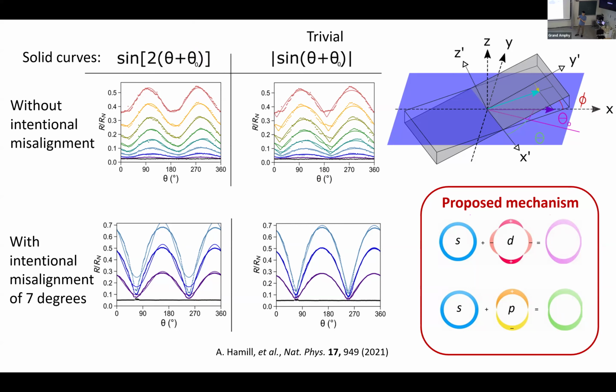However, I think maybe there are some tuning parameters that we may not really account for. Maybe this trivial effect is not just that trivial. We need to have something else. However, if we are really serious about this twofold symmetry, then they propose that the pairing order parameter is not just pure S wave, because S wave is isotropic. Then you need something to give this twofold symmetry. So either it's S plus D or S plus P. If it's really P wave, it goes in line with the spin triplet pair scenario.